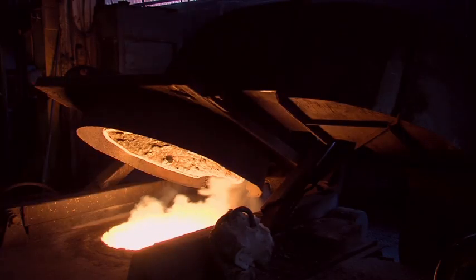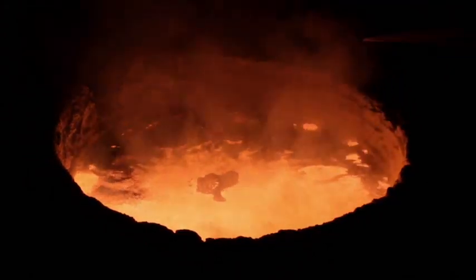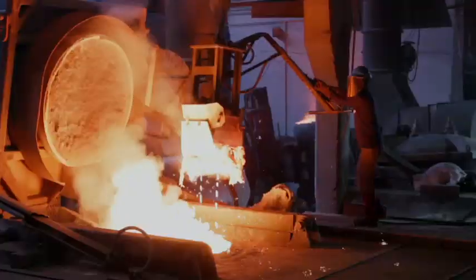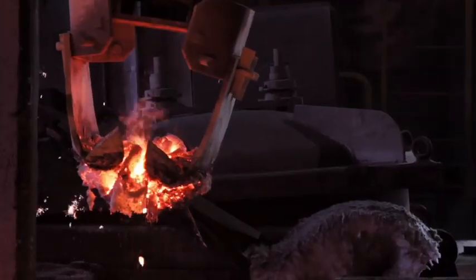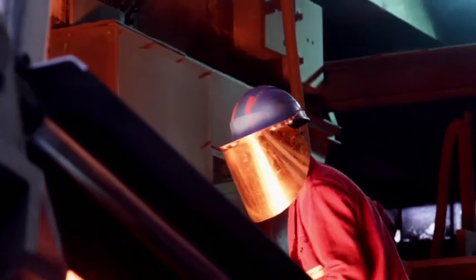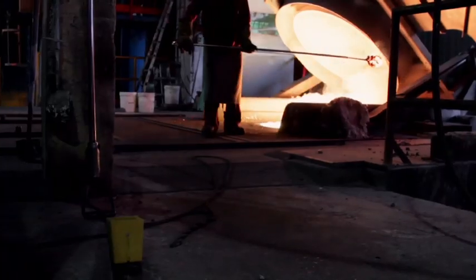These are then melted at 1500 degrees C in our 6 ABB induction furnaces to make one of Betsaide's materials: ferritic ductile iron, pearlitic ductile iron, or grey iron. The relevant chemical analyses are also performed in the furnaces prior to tapping.